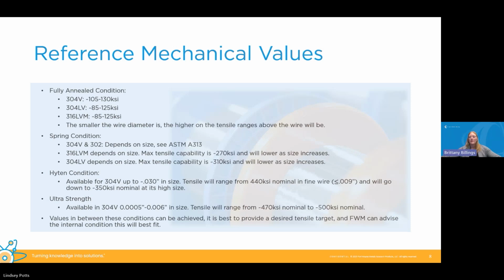increases. In our Hyten condition, that's going to be available for 304V, and that's up to about .030 in size. The tensile will range from 440 KSI nominal in fine wire, and then we'll go down to about 350 nominal at higher sizes. And then the ultra strength, so this is just speaking to our stainless steel 304V. Ross is going to cover our tungsten, but the size is 0005 to 006, and the tensile range is going to be about 470 to 500 KSI nominal.